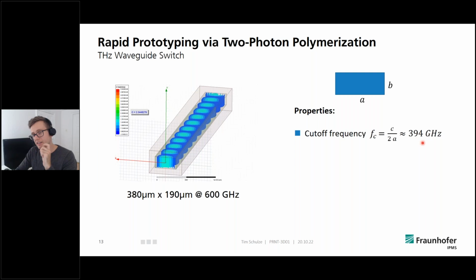We actually had this idea of developing this in silicon as a real silicon chip, but it was very exciting to also try this with a printed object, because the resolution we are able to obtain when printing structures in a silicon chip approximates, in the same order of magnitude size-wise, the resolution of this printer. And that's why we did a rapid prototyping approach to print this switching capability inside a printed component.